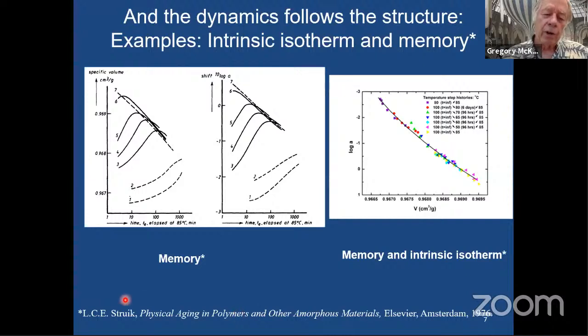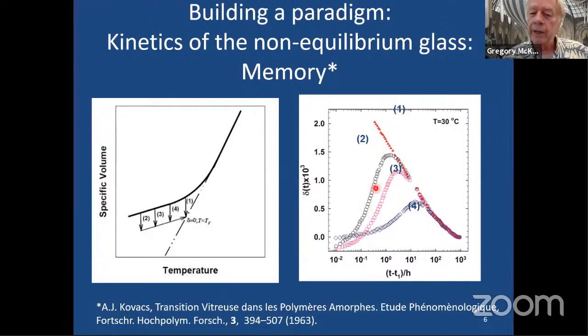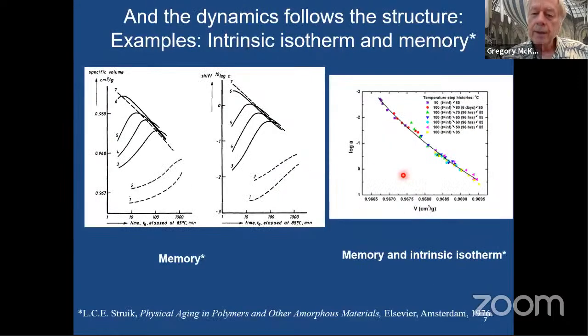So later on, Struik showed that the relaxation times in the volume measurements compared to the way that the mechanical shift factors behave, you can also get a memory effect in the shift factors, which might be expected because as the volume is changing, you would expect that the relaxation times are changing. And Struik showed that within a reasonable experimental uncertainty, the actual value of those shift factors or the relaxation times, because the shift factors are a scaled relaxation time, are independent of the history. So the dominant piece of that is that the free volume in his way of thinking determines the relaxation time.